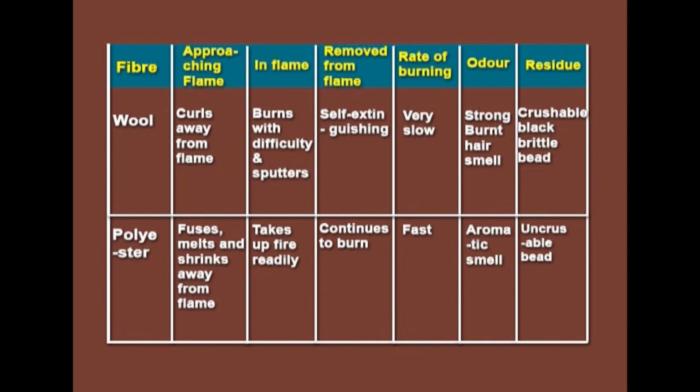In the flame, it takes up fire readily, but it continues to burn even after removing from the flame, and the rate of burning is faster, but it is a little slower when compared to the cellulosic fibers, and it gives an aromatic smell. The most important thing here is the residue. It gives an uncrushable bead.